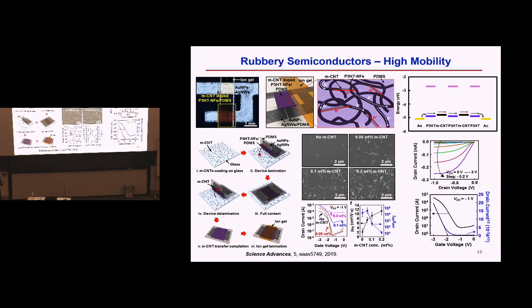Why? It's because we're utilizing these metallic carbon nanotubes. It's because of the very high carrier mobility through the metallic carbon nanotube. But also, they actually provide fast tracks, and have a good interface with the semiconductor materials. So we utilize these metallic materials, high mobility, and also the work function match with the HOMO level of these organic semiconductors, nanofiber structure, to allow the carrier to easily flow. So, utilizing this, we have the 3 material system.